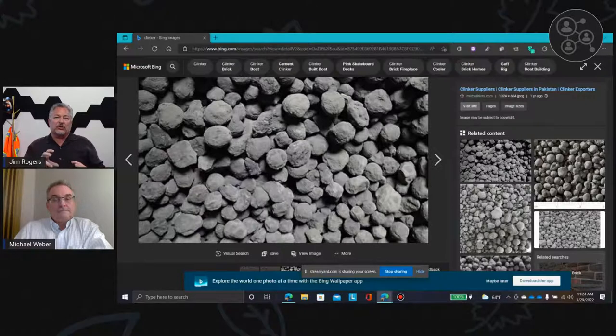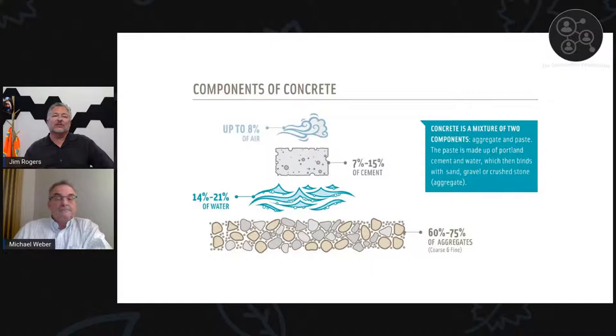So Mike, what you're saying is that the Portland limestone cement is produced by taking about 10 to 15% of this clinker away and just putting back limestone and then grinding that product all together into the fine powder that still just looks like cement. So in my concrete, if I can throw this slide back up here, I'm still going to use the same amount of Portland limestone cement as Portland cement, but that Portland limestone cement is now blended with some limestone. So I've reduced the carbon footprint of just that one little ingredient by like 15%, right? Correct. Typically anywhere from 10 to 15%.